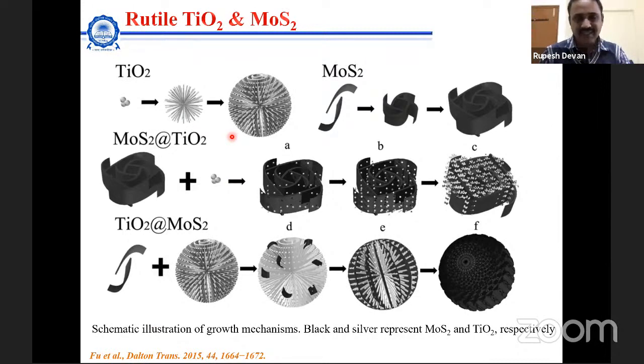but their thinking was different. They used this buckyball kind of thing. Actually, this is not a buckyball. They created spherical nanorods, and then they tried to cover them with MoS2 in a two-dimensional structure. So their idea was to cover the one-dimensional and two-dimensional structures together, but it did not happen, because when they used MoS2 as a template, they couldn't create these one-dimensional nanorods of TiO2, but they created particles over it. So they considered two heterostructures. One is MoS2 covered by TiO2 and the other is TiO2 covered by MoS2. But their idea was to cover a single nanorod.